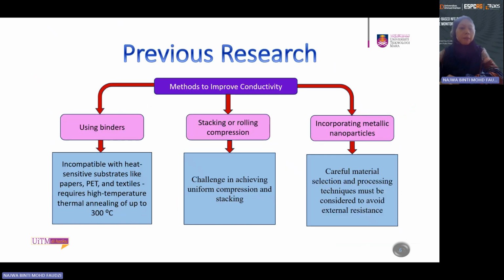There are a few methods that have been applied to increase the conductivity of the graphene-based material. For example, by using binders to prepare the graphene ink. However, the binders are incompatible with heat-sensitive substrates like paper, PET, and textile, as they require high temperature thermal annealing of up to 300 degrees Celsius. Other methods, for example, stacking and rolling compression, have also been used to increase the conductivity, and they are suitable for heat-sensitive substrates. But the challenge is to achieve uniform compression and stacking.